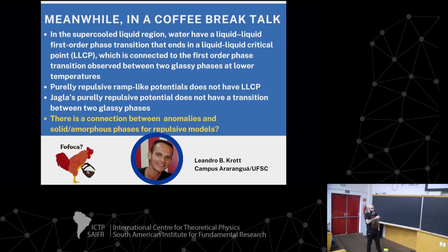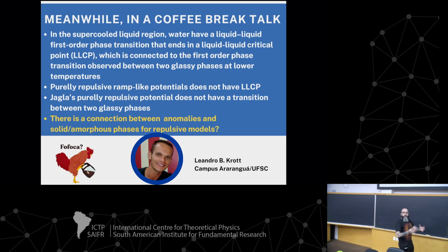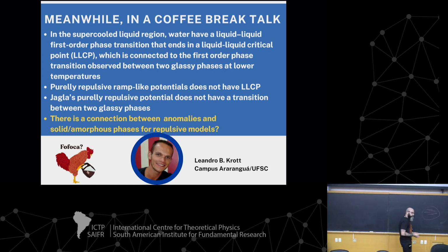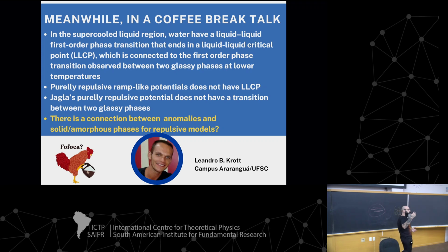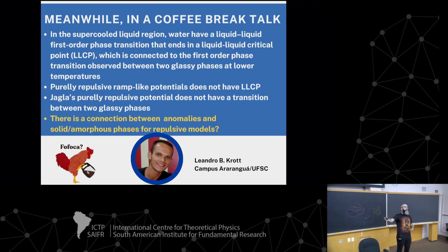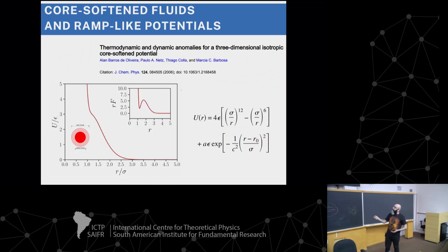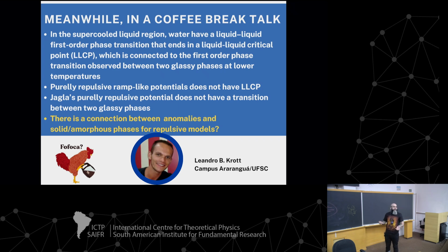OK, so supercooled water has the liquid critical point. And we believe that for real water, this is what creates all the anomalies. But if you have a purely repulsive potential, you cannot have critical points. So that potential does not have a liquid critical point. So what was the question? Is there any kind of connection between the anomalies and, maybe, a solid or amorphous phase for this purely repulsive model? And why an amorphous phase? Because remember, in real water, we believe that the liquid critical point is connected to the transition between the two glassy or the two amorphous water states.